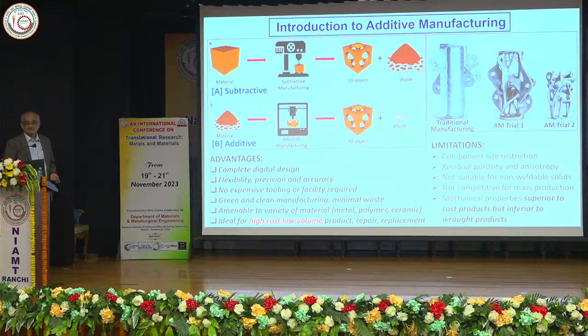There are disadvantages as well, and one has to be realistic. These mainly come because of possible defects we may incur. The whole process is essentially a droplet integration process, whether it's a polymer or a metal. When you fuse two droplets, and have multiple of them joining one after another in series, there's every possibility you trap porosities, or during shrinkage you may be left with shrinkage cavities which may turn out to be internal cracks or defects.